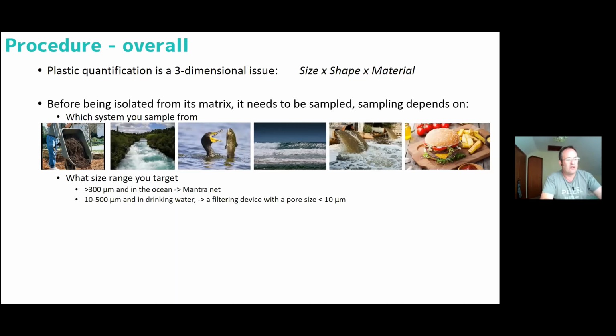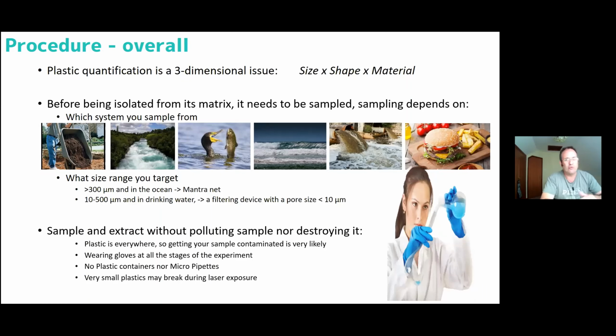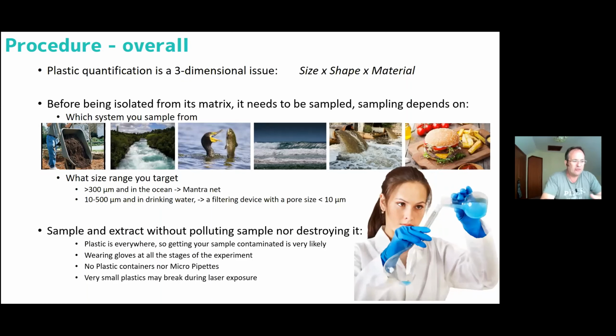So in an ocean, for example, for something 300 microns and over, you might use a manta net. If it's in drinking water, between 10 and 500 microns, then you might need to use a filtering device, typically with a pore size of less than 10 microns. So this is even before you actually look at it with a characterization tool, maybe a photonics type tool. And of course, when you're doing this, you want to sample and extract without polluting the sample. So you don't want to add plastic, and of course you don't want to destroy it either. And plastic is everywhere, so getting your sample contaminated is very likely.